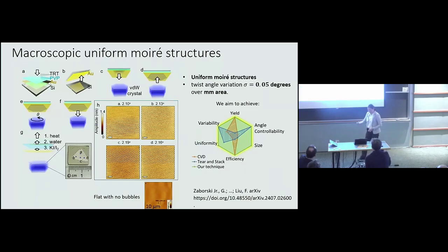And we also did an XPS on the surface to see if there is any remaining gold, and we don't see any gold signal on the surface. So this chemical removal of gold is complete. The reaction is very efficient, 100% yield.